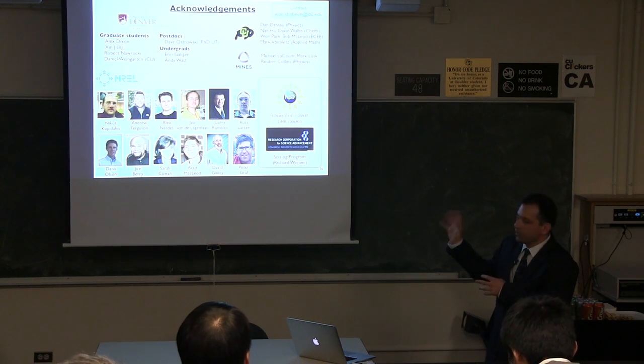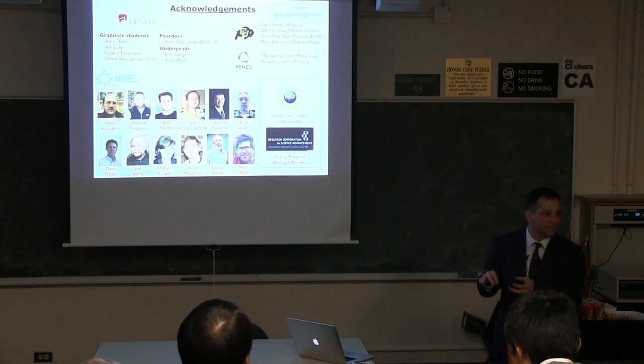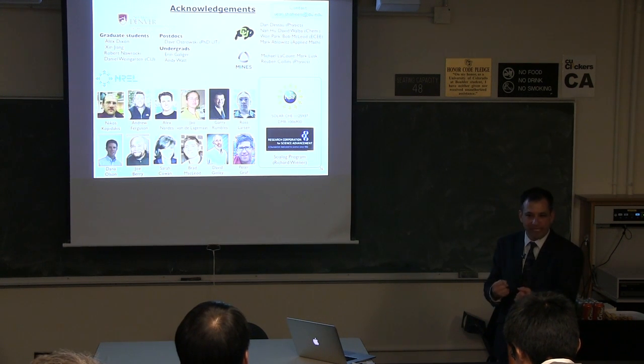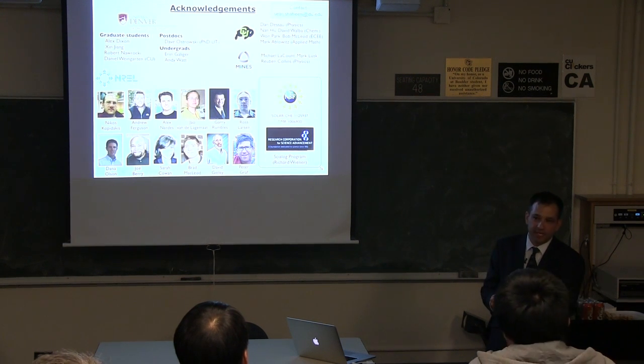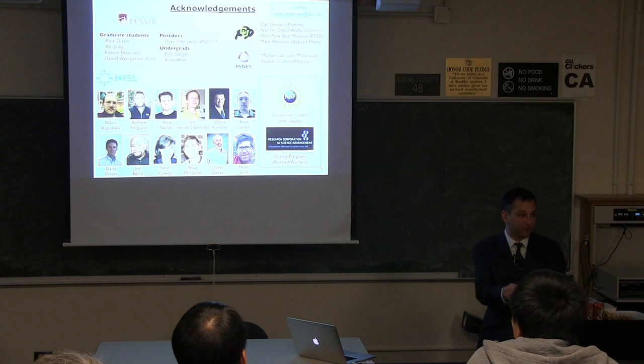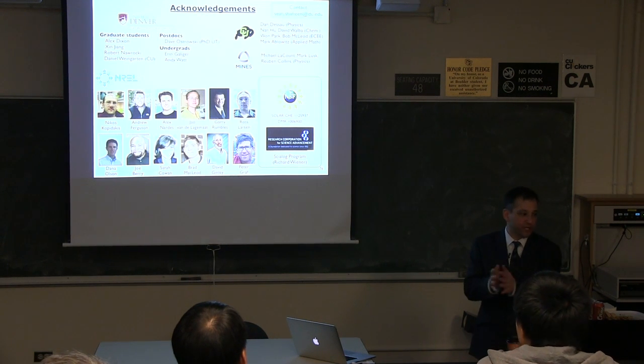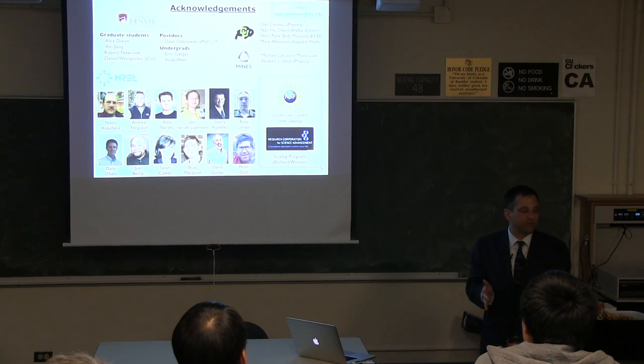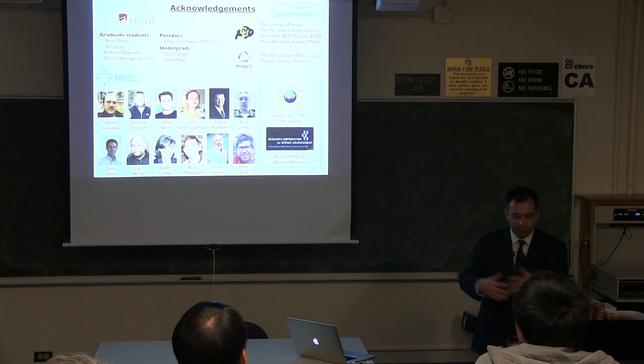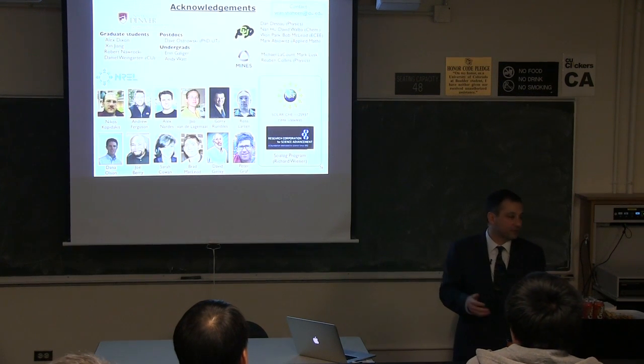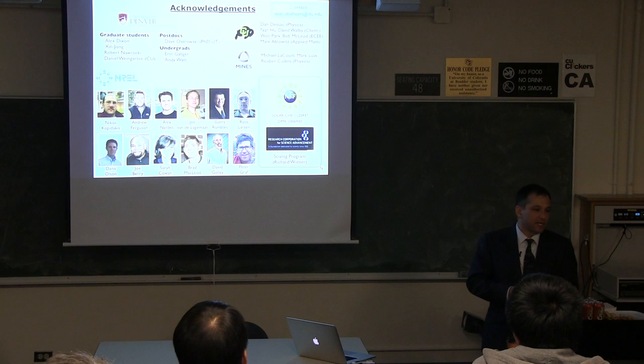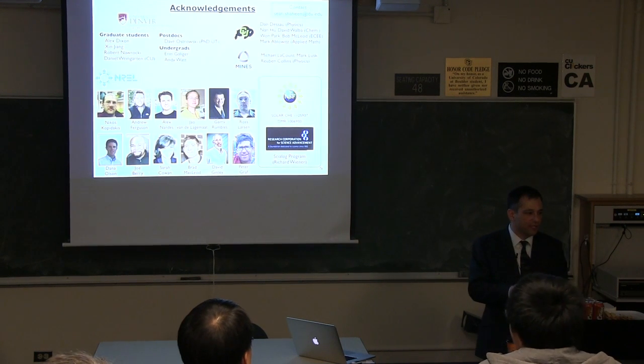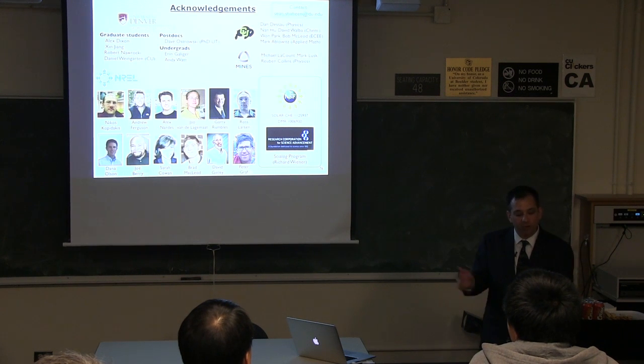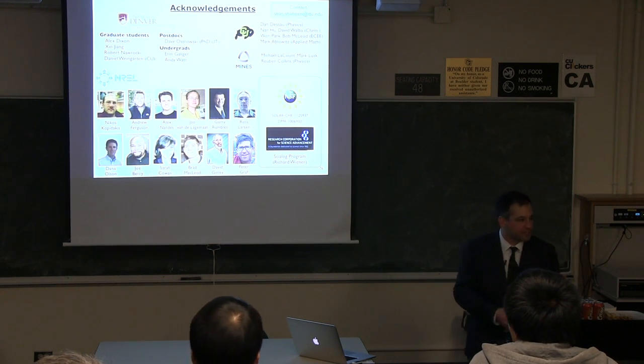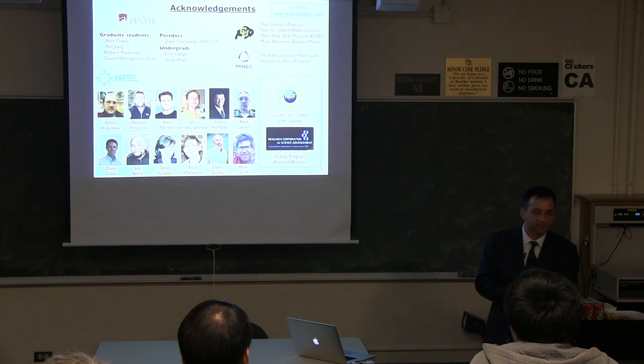One of the theories now is that there are 3 dominant phases in the material. There is a very amorphous phase where donor-acceptor are intimately mixed, and in that phase, you get very rapid carrier generation because there's an exciton always next to an interface. But that's a very poor material for transporting the charges. So beyond that are two additional phases that are a lot more pure, that do the transporting. In some sense, it would self-organize into three components that separate the behavior of the device, charge generation and transport. The issue is that it's really hard to tell if a given phase or domain is actually pure. If you had 99% donor, 1% acceptor, TEM and NEXAFS can't really tell us that at present. So that's the issue.